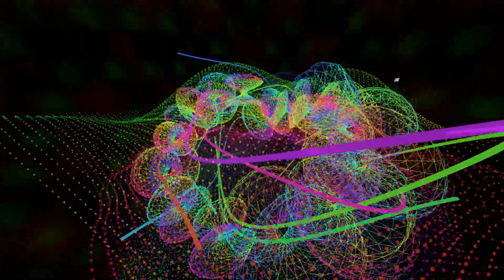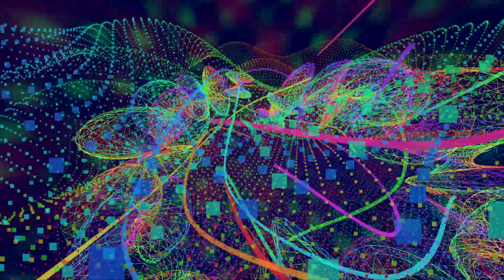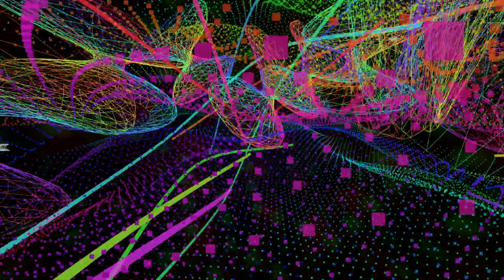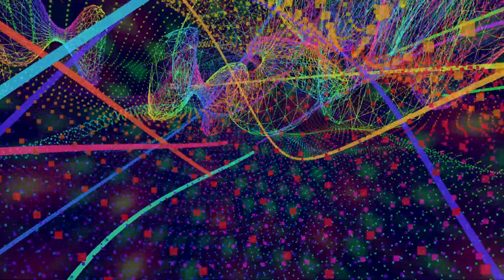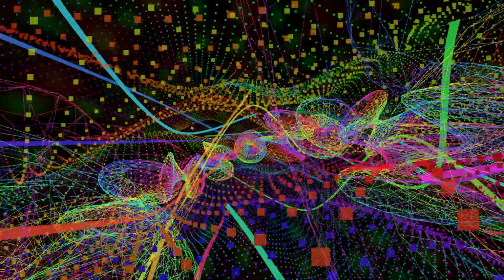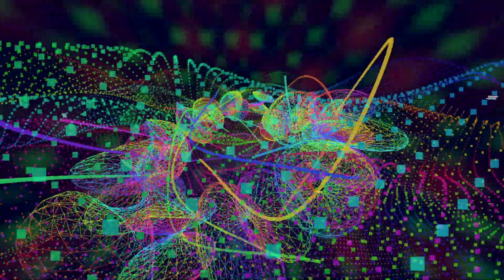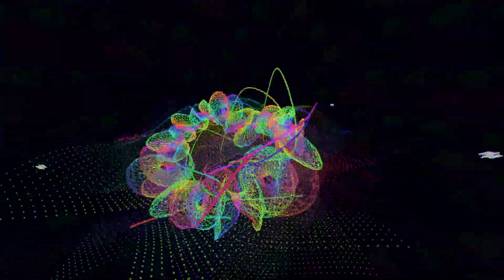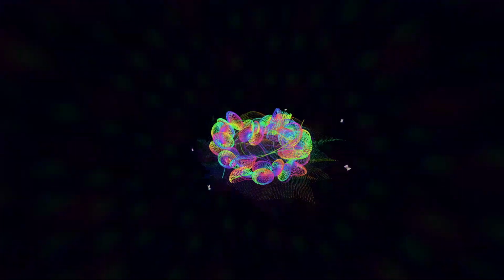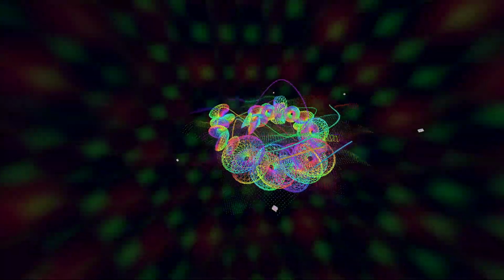Then there's the opposite problem, thermalization. This happens with the high-energy photons, blue light, UV light. They have way more energy than the 1.12 eV needed. They easily kick an electron across the gap, but they kick it way up high, energetically speaking. And that electron very quickly loses all that extra energy above the band gap. It just relaxes down to the edge of the gap and the excess energy is lost as heat again. Wow, so losses on both ends. Too little energy is wasted. Too much energy is also partly wasted.